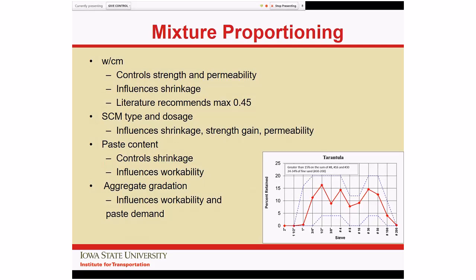The literature recommends for bridge decks a maximum water-cement ratio of about 0.45. I would also put that in as a pretty good minimum. I'd hesitate to go much above that. So let's settle on 0.45 as a fairly good water-cement ratio for our specifications. Our supplementary cementing materials will influence strength, the rate of strength gain, and impermeability. Depending on the product that you're using, and in your area, slag is the preferred and available material. In the range of 35 to 50% seems to be a pretty good number for that material. Again, balancing that shrinkage, rate of strength gain, and getting the good permeability that we're looking for.